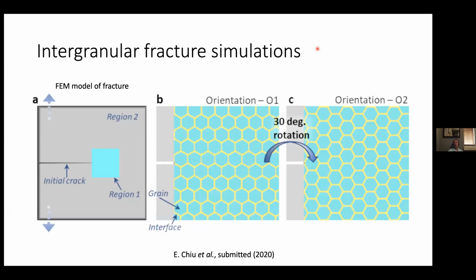Meanwhile, in a model such as the one I was showing you before, these are finite element models, so they represent the material as a continuum, and they homogenize, they average over the properties. They assume that every point in this model can be thought of as a representative volume element of the material, and so the response of that material is going to be described using a generalized Hooke's law for elastic behavior, and in this case, J2 plasticity for the plastic deformation behavior. The numerical method for solving this model is going to be a partial differential equation solver, such as the finite element method, whereas to work with that atomistic model, we would use ordinary differential equation solvers to propagate the atoms forward through time along their trajectories.